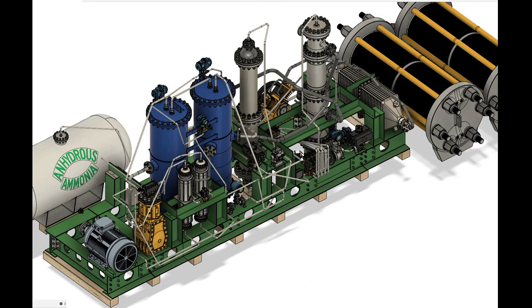What can be deduced from this is that ammonia kinetics are highly thermally dependent, with the same elements exhibiting dramatically altered performance at different temperatures. This is the main reason the huge efforts by catalyst researchers to find a low-temperature catalyst have yielded such poor results. One must remember that ammonia synthesis is a reversible reaction.